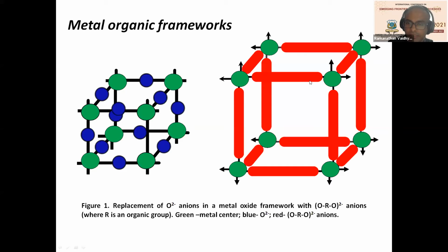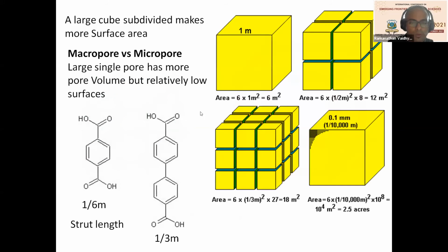And also these, every red line you see here is a surface. Okay, and these are the surfaces where gas molecules can interact very well. It can interact with the red line as well as the green ball, which is a metal center. Now you can see that by subdividing a big cube into smaller cubes, you can increase the surface area very systematically. So which means if you replace a longer linker by a shorter linker and divide it into smaller cubes, you have a chance of having very high surface areas.